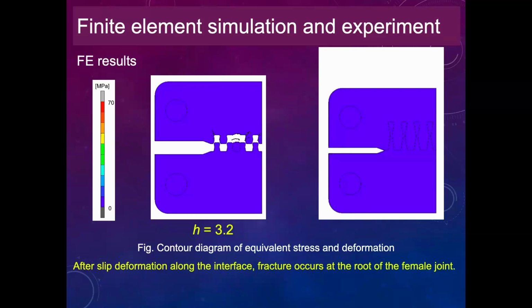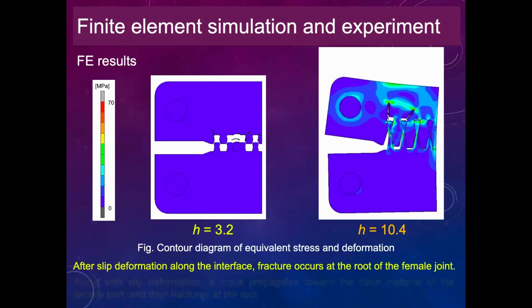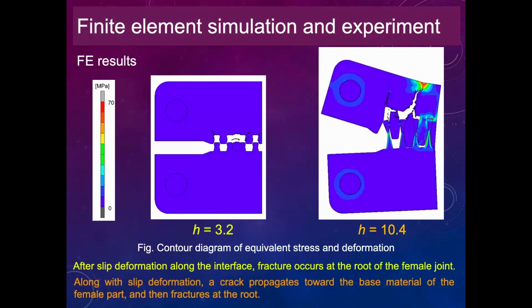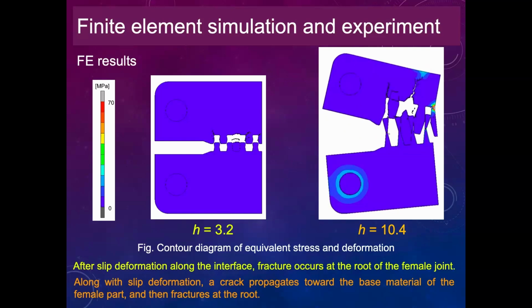On the other hand, this is the case for H equals 10.4 millimeter. From this animation, along with the slip deformation of the female joints, the crack propagates towards the base metal of the female part, and then the fracture occurs at the roots.